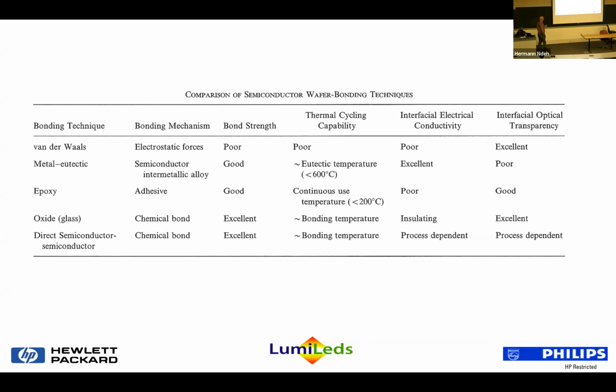What's unique about this is that you can get excellent bond strength. You can thermal cycle the devices nominally up to the bonding temperature, so they're very robust to processing after the devices are bonded. We'll talk about how, if you do it right, you can actually get very low resistance across the wafer bonded interface, as well as very good transparency. And in total, these properties allow you to make the best red, orange, yellow LEDs, and it's actually important in other areas as well. We'll talk